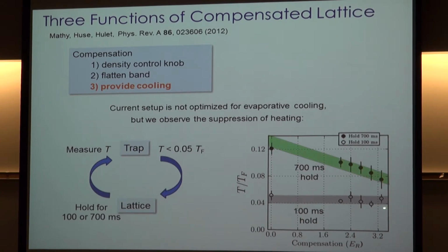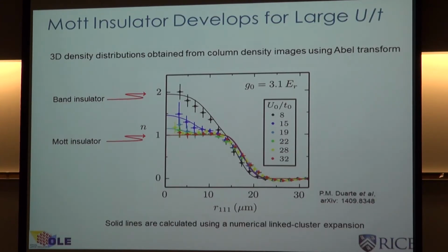So this is a hold time of 100 milliseconds in this gray band. And this is a hold time of 700 milliseconds as a function of compensation intensity. And you can see that if you hold without compensation for 700 milliseconds, the temperature goes from 0.04 to 0.12. And that's because of all those technical sources of heating that I was discussing earlier. So the compensation mitigates that. So we actually don't have good evidence that we're doing evaporative cooling in the lattice, except that we know that we can mitigate heating in the lattice. And that's very, very important because that's a limitation in all lattice experiments.